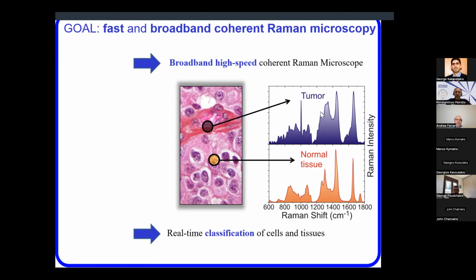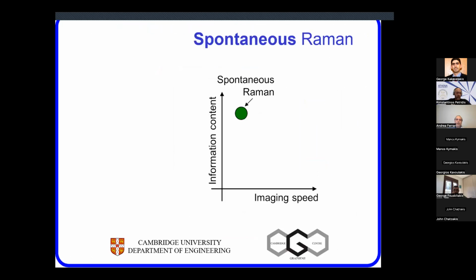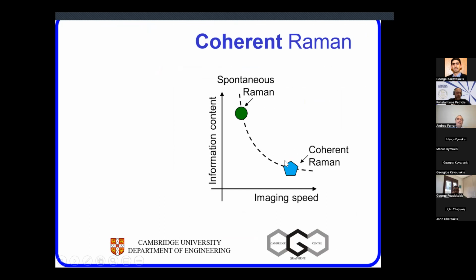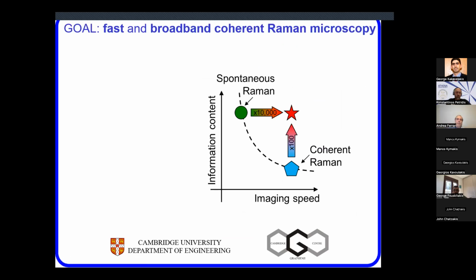So each pixel corresponds to a spectrum, and that allows you to tell if the tissue is tumor or not, but not based on a judgment that you make, based on the chemistry, based on the chemical signature you see. So what we need to do is to go from spontaneous Raman that gives you a massive information content. Coherent Raman is very quick, but very low resolution. We need to get a sweet spot there.